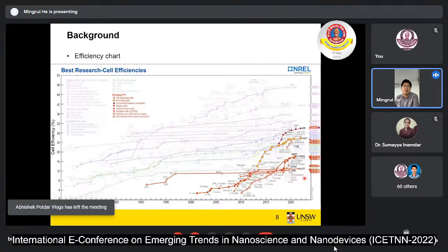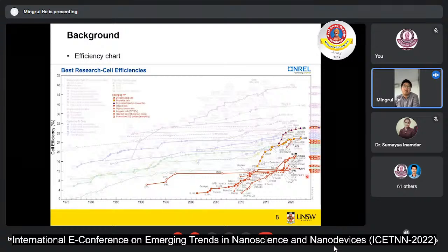Here, the currently certified record efficiency for the CZTSSe solar cell is only around 13%. This efficiency was just achieved last year by a Chinese group. Before that, CZTSSe solar cells had not improved a lot during one decade because of a few crystal defects, which I will mention later. Compared with the other types of solar cell, as many of you know, the perovskite solar cell has already achieved high performance, made by a group from Korea. They already got 25%. It's an amazing efficiency, and it could be promising for the next generation solar cell.